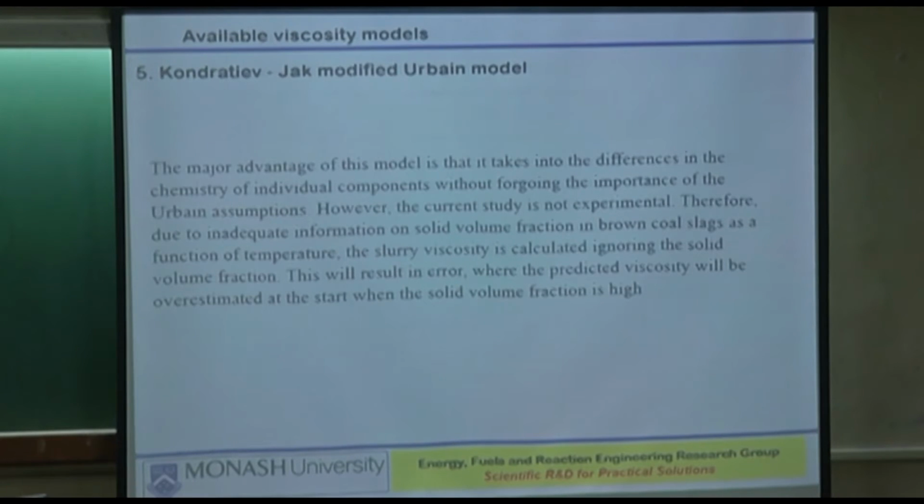So those have to be recognized, but you can make predictive calculations, assuming 5%, 10%, 20%, etc. being crystalline solids, or the solids fraction, and then see what viscosity this model predicts, and then whether that matches with your expectation or not. So we'll see that.